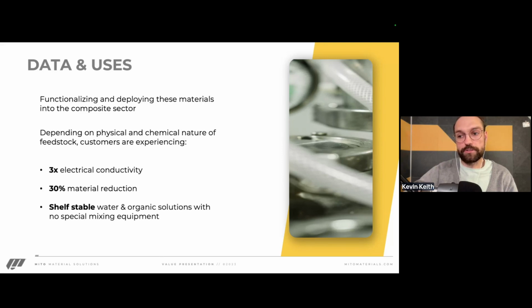So they're able to just disperse it in on site, make parts. And what they're finding is that with 30% less material and 0.1% of our product, they're able to create a much stronger system that still passes QA/QC.